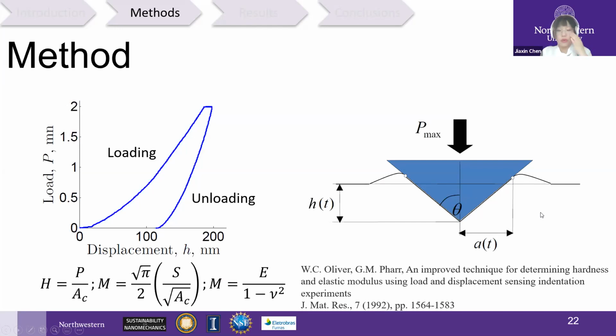Let's take a closer look at the indenter and the raw data from the indentation. This is a curve with load and displacement. The left-hand side is the loading part, while the right-hand side is the unloading part. We used a Berkovich diamond indenter on an Anton Paar nano hardness tester. Vertical force P and penetration depth h curves were obtained from the depth sensing equipment. We applied Oliver and Pharr's method, as shown here,